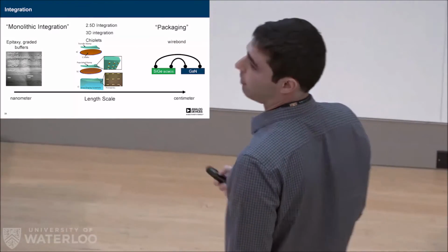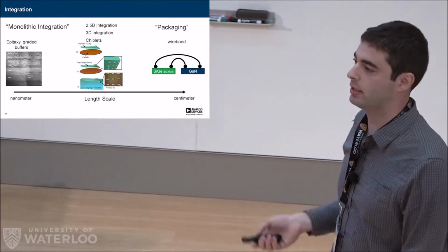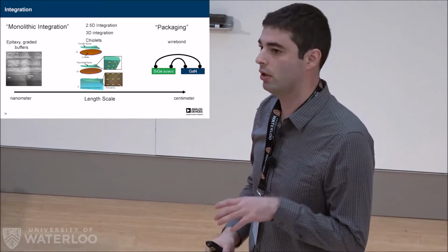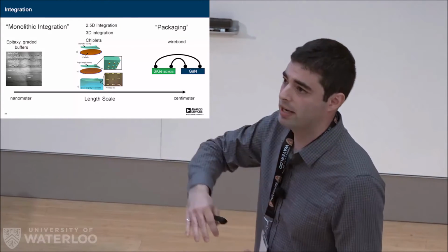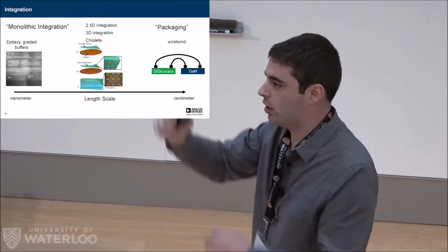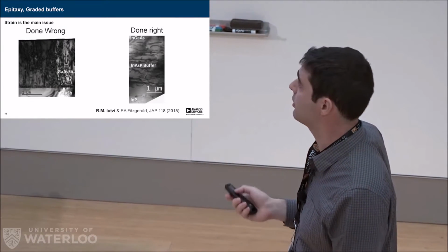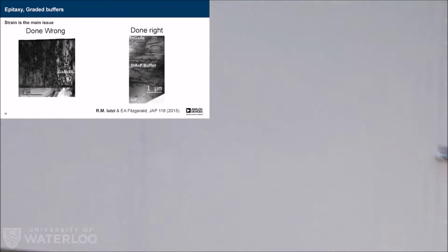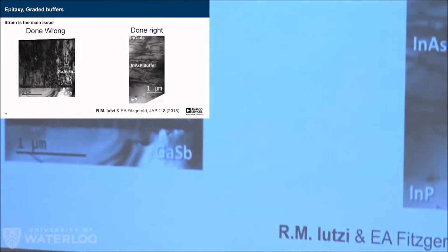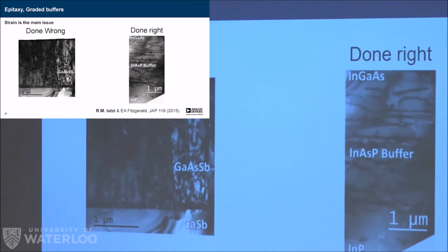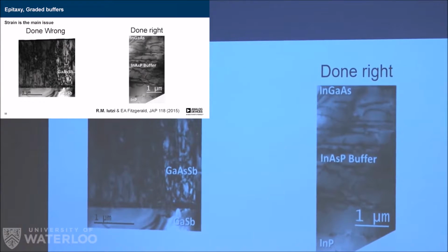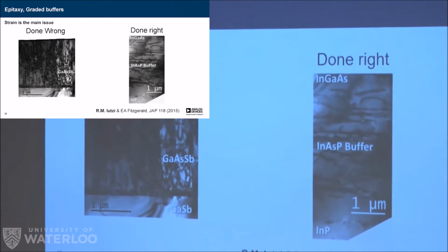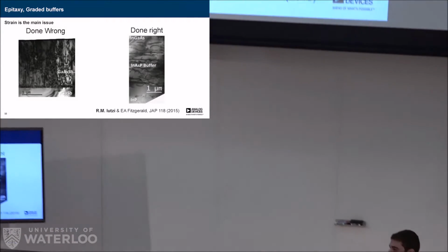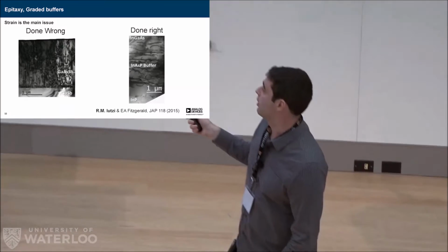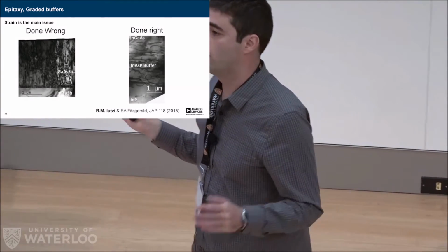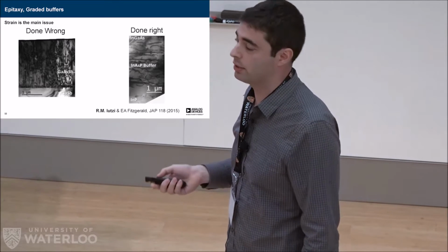So you might think, well, let's just go to the smallest scale possible because then everything will be great. And the smallest scale possible is just having a single crystal with the different materials. Say I'm trying to combine GaN and silicon, have a single crystal where it's just all one piece. And this is an active research area, but it's not that simple. So here's an example where I tried to combine gallium arsenide antimonide with gallium antimonide so I can have two different devices. But you see all these black defects everywhere, and the reason is because this material has a different lattice constant. So it's going to form dislocations which are going to try to relieve the strain. And the result is that they're everywhere, and holes and electrons just recombine there, and the device doesn't work.